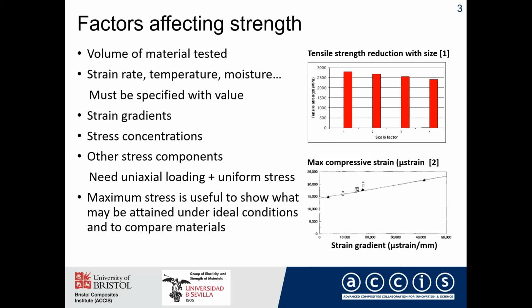So let's talk about some of the issues, some of the factors affecting strength. One of the factors which is still not widely appreciated or recognized is the fact that the volume of material tested affects the strength. So you see on the right that there's some results for tensile strength of different size unidirectional carbon fiber epoxy. And you can see that as the size of the specimen increases, then the strength reduces from about 2,800 megapascals down to about 2,400 megapascals.